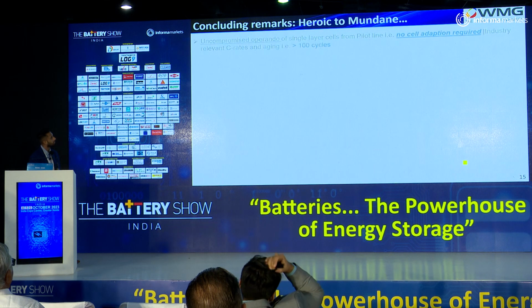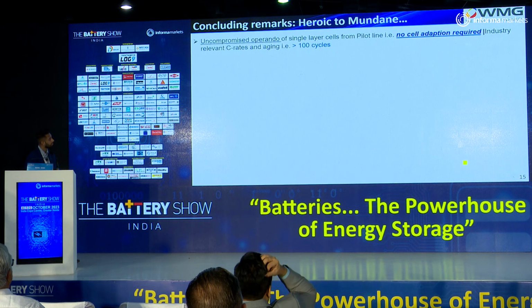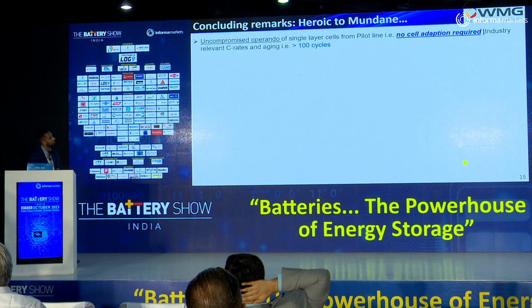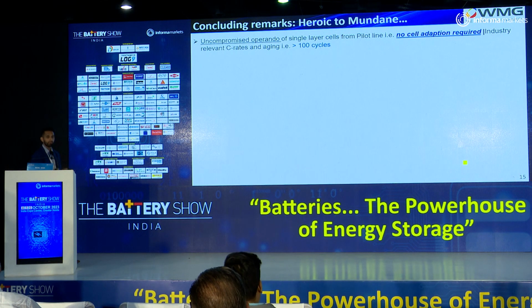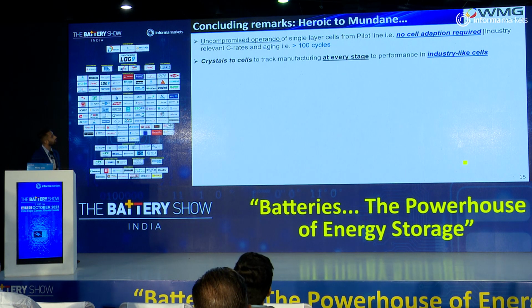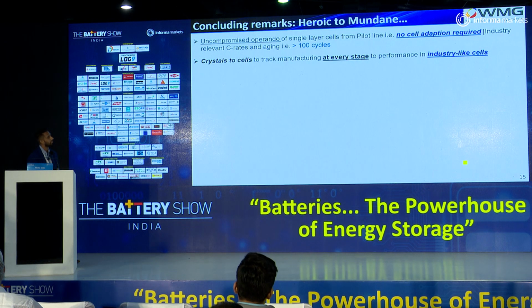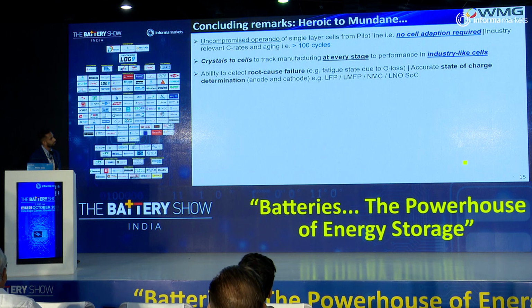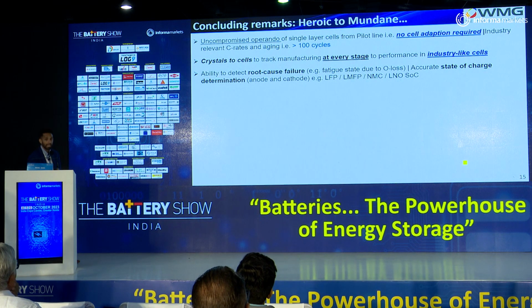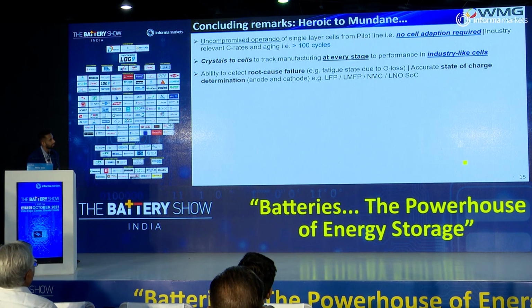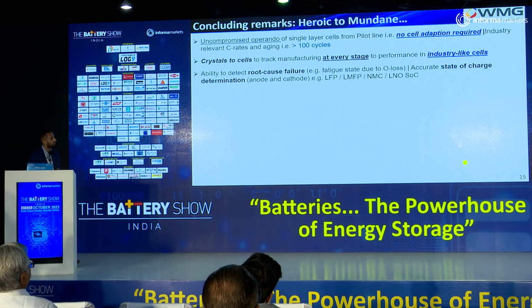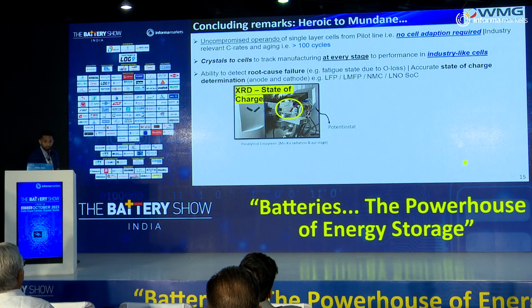So, for our concluding remarks and how we actually do these measurements and what instruments we use. We can synthesize uncompromised operando cells and have complete control from the powders, from the crystals, all the way to the cells through every process in industry-like cells using a multitude of chemistries. And we use chemistries such as LFP, we are branching into LMFP, NMC, and even nickel-rich LNO materials, so 100% nickel materials. So how do we actually perform these X-ray measurements?